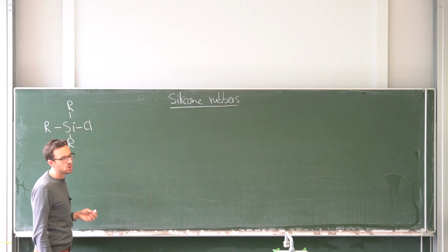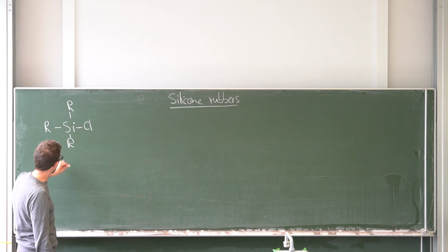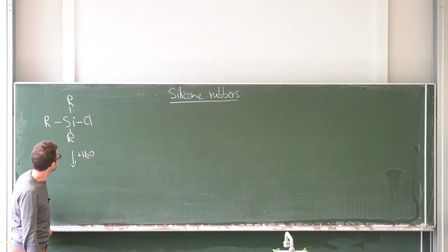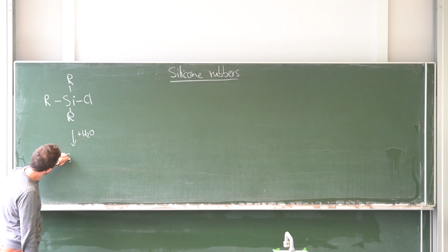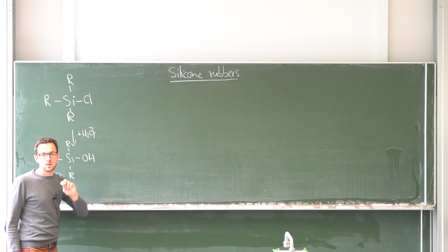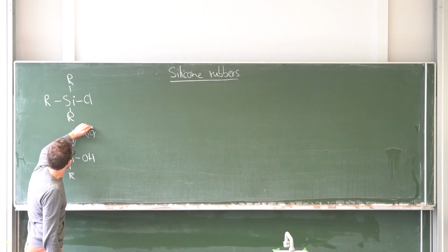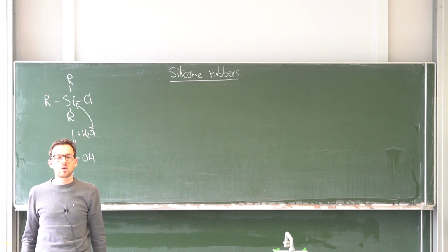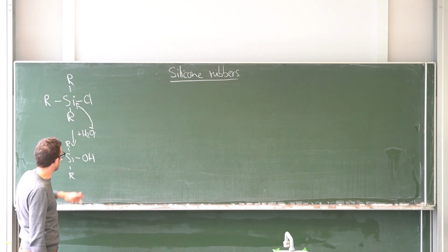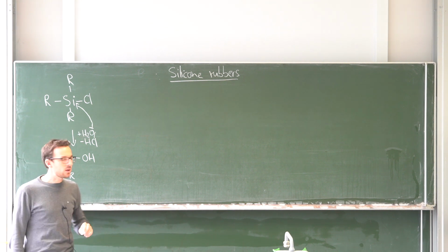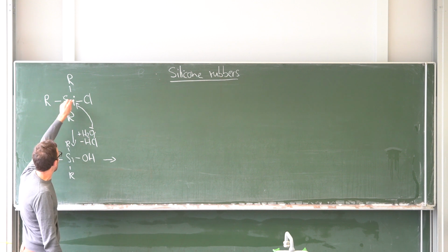And it can also contain chlorine groups. And these chlorine groups, when they come in contact with traces of water, they will first hydrolyze. And why is that? Because water, again, is nucleophilic. So the high electron density of the oxygen can make a nucleophilic attack on the silicon because this will be partially positive as a result of this highly electronegative chlorine as a neighbor. And then it will kick out the chlorine and you will get this type of material.